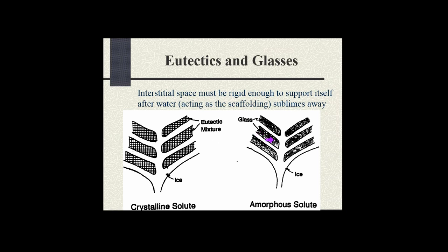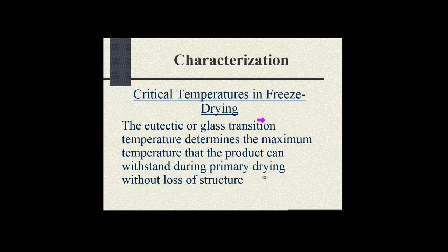Now, these two trap water very differently, so identification is key. For a completely crystalline system, your product at the end of primary drying may already be 99.99% dry. For an amorphous phase, you could still be retaining 40% of your moisture locked in this amorphous phase, so identification is key. Okay, well, we talked about that. It determines the maximum temperature that the product can withstand during primary drying without losing structure.